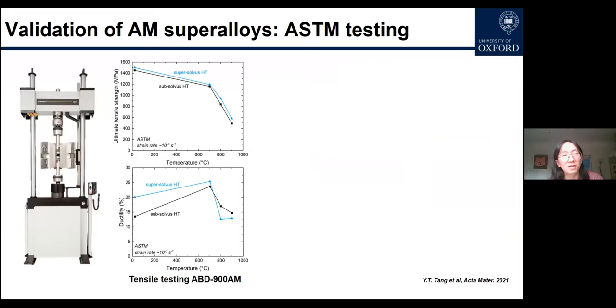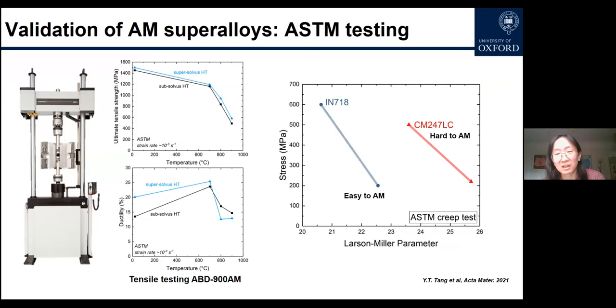As part of the process to understand how good these materials are, they were tested by third parties to ASTM standard. And you can see the properties are still quite good, very similar to what we anticipated from our miniaturized testing. And of course, for high temperature applications, you can't escape creep at all, which is really important.